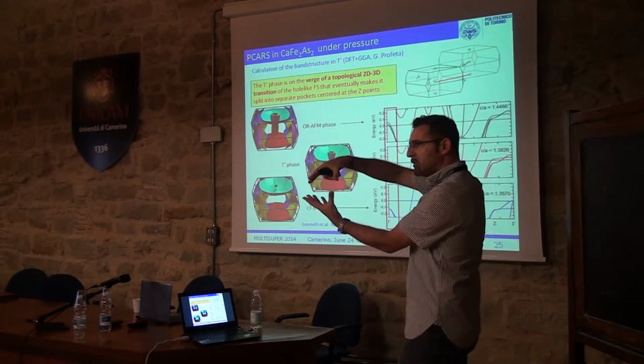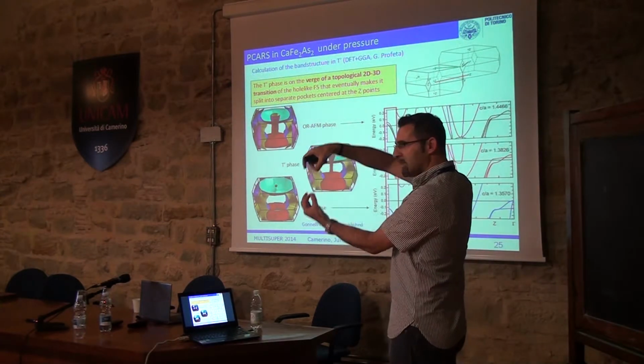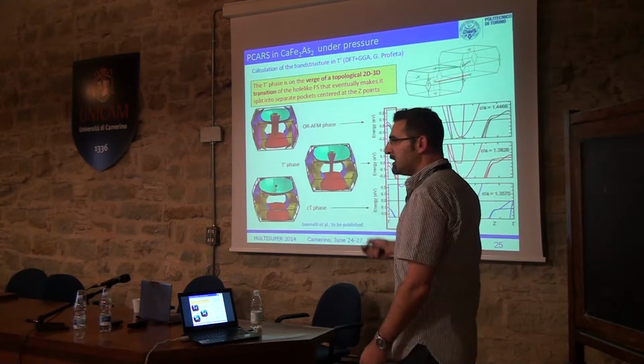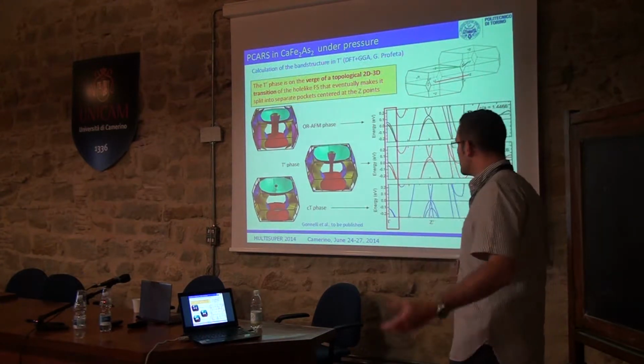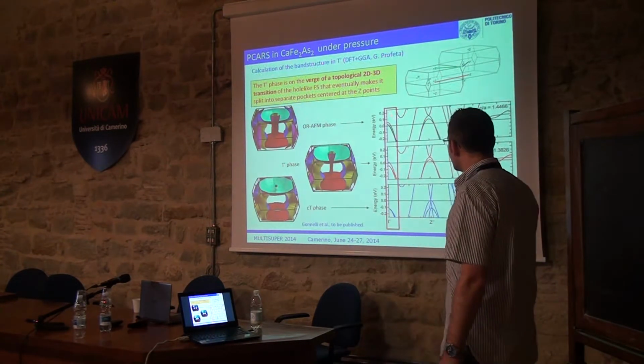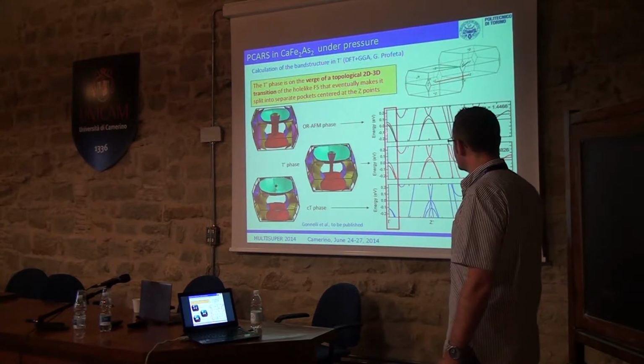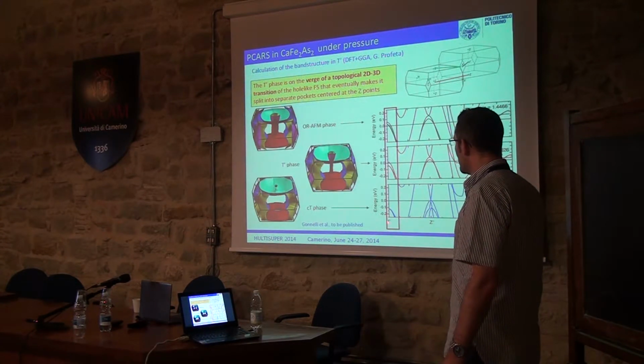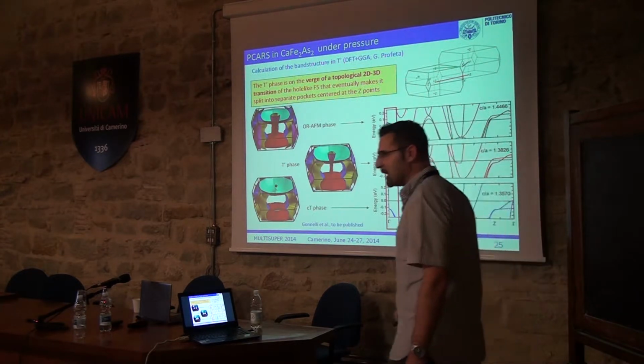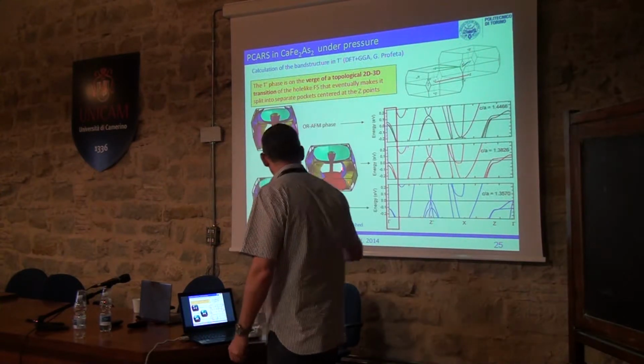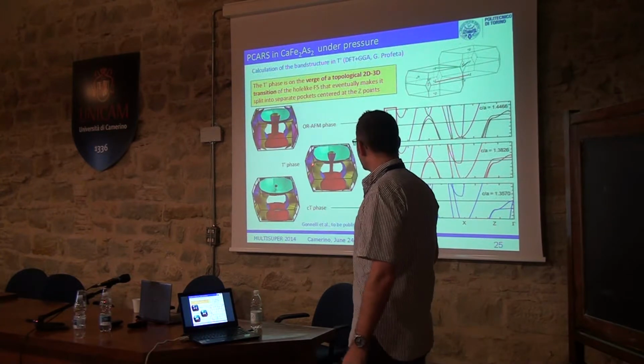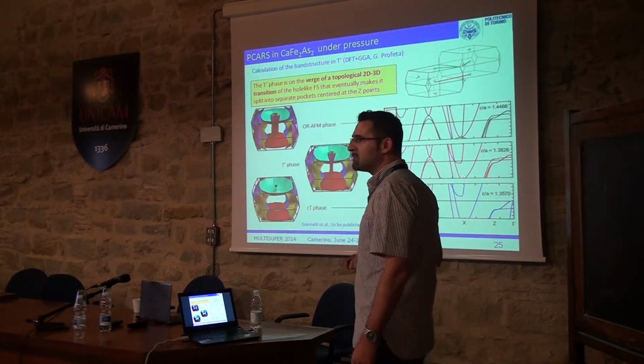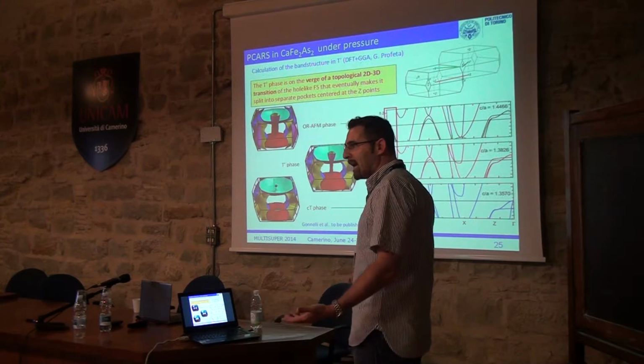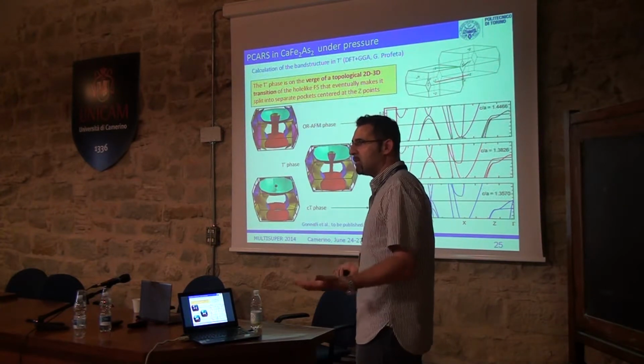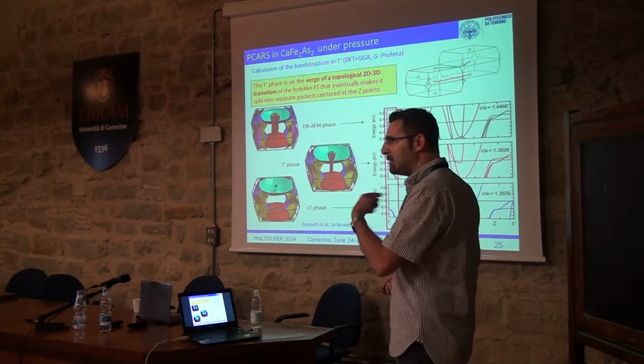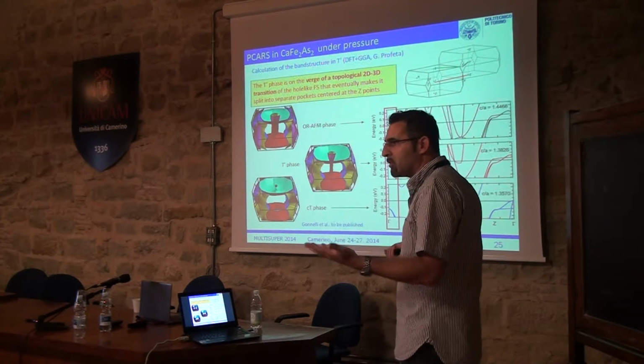So the Fermi surface is going to split into separate pockets. This is very interesting because it is again in agreement with what we have seen before. And this is just a picture of the band structure. You see that there is a progressive disappearance of the hole-like band around the point gamma. Now we know that this is the Fermi surface, and we know that this Fermi surface must host also gaps, one more or less isotropic and the other one which has probably an in-plane anisotropy and has some nodes or zeros, we don't know exactly.